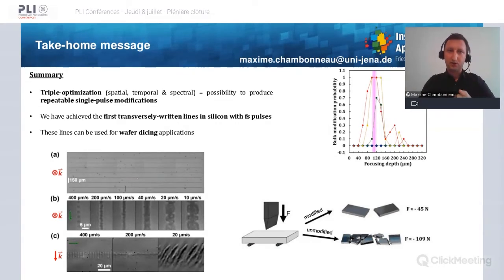So here is the take-home message for this last part. With a triple optimization in spatial, temporal, and spectral domain, it is possible to produce repeatable single-pulse modifications. We have achieved the first transversely written lines inside silicon with femtosecond laser pulses. And these lines can be used for wafer dicing applications.